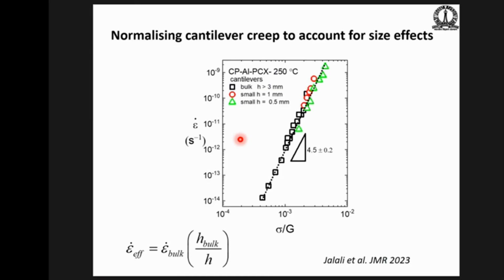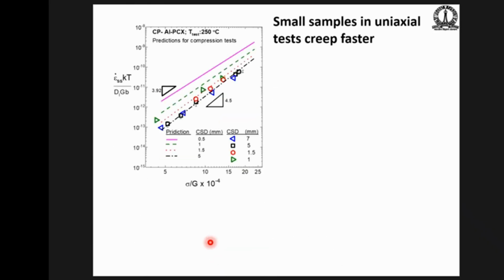So you can standardize this. You can normalize it and bring it to a length scale independent parameter, which is shown here, except one doesn't know what H bulk is. So this is a fitting parameter. If you use a certain value of H bulk, then anything smaller than that, you can show scales linearly with the magnitude of that ratio.